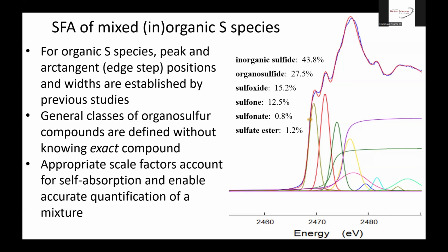I wonder if it was ever compared against a known linear combination of known species, like a physical mixture of species where you know what they are. Yeah, there's a paper, and I'm going to provide some references to upload to the webpage about this. One of them will be a paper by Prietzel et al., who did, in soil science, a comparison between linear combination fitting and a form of spectral feature analysis. And their results were basically the same thing I just said: if you have really good spectra of your standards, linear combination fitting works better. If you have more variability or uncertainty in your compounds, which you often do in natural materials, the spectral feature analysis is a better approach.